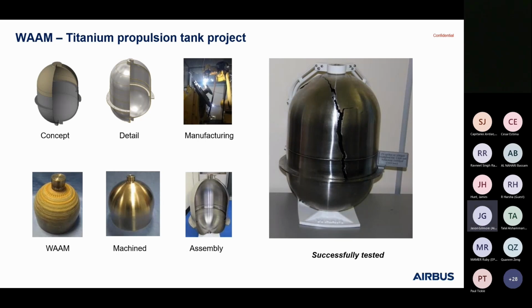If you look at the picture on the bottom left, we talked about a substrate plate. Could it be part of the final product? Well, that's quite a key point, because on this project, we actually used a round bar, and this gives you an advantage that you can now use this to help datum your 3D scan, because you can overlay the as designed against the as built in CAD to work out if you put enough meat on the bone that you get a full cleanup. So that helps you datum it for the CAD inspection, and also the alignment on the machine as well. So really quite an important point.